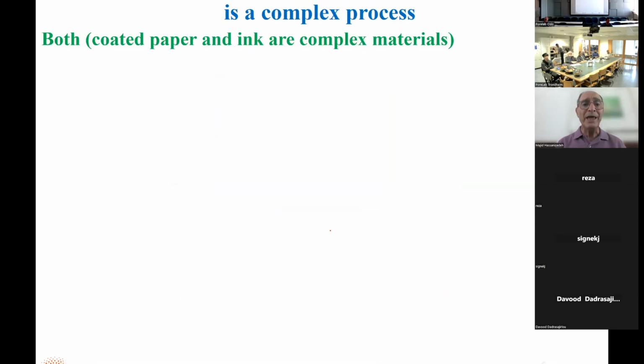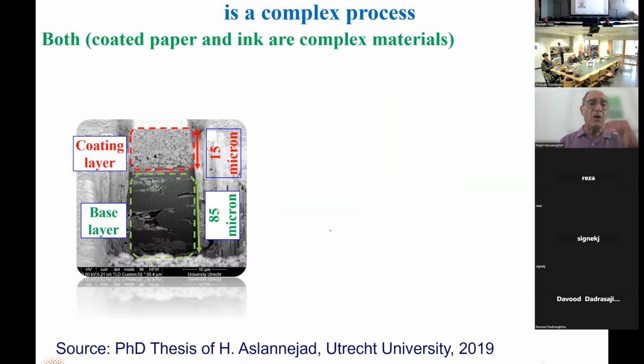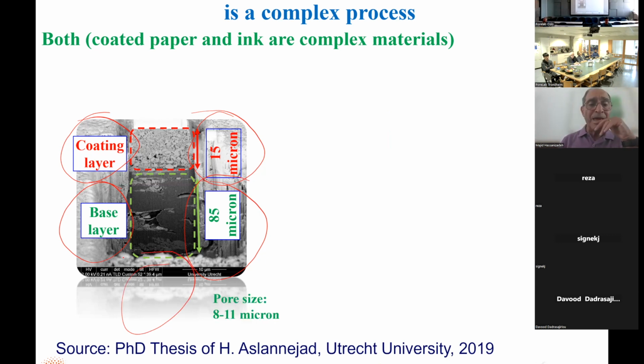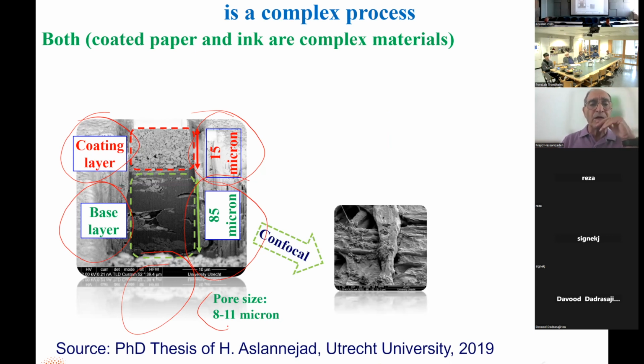So both paper and ink are complex materials. We have studied the paper. The coated paper has a coating layer and a base layer. Now here, in this example, the base layer is 85 micron thick, but it could be up to a couple of 100 micron, and the coating layer typically 15 micron to 20 micron thick. And there is, of course, coating on the other side as well. Now, this base layer is a fibrous material. It has pore sizes of 8 to 11 micron, and we can therefore use confocal laser microscopy to image that layer. And you can also use CT scanning to image it.